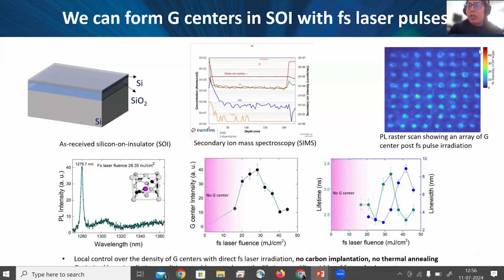Now at this stage, everything is still located at random places. So the color centers we are making are randomly oriented in the lattice. Now what we would like to do is manipulate them locally so that we can erase them from the places we don't want them and keep them, or write them with desired properties, where we really want them. And to do that, we wanted to use femtosecond laser pulses.